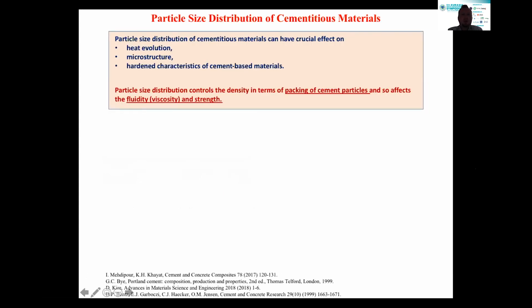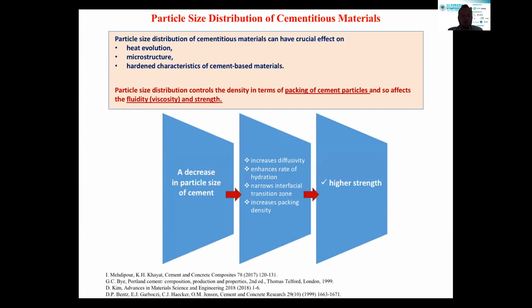structure. So what's the importance of the particle size distribution of cementitious materials? Particle size distributions have an effect on the heat evolution, microstructure, and hardened characteristics of cement-based materials. So the particle size distribution controls the packing of cement particles and also affects the viscosity and strength of the cement mortars. When the particle size of the cement decreases, we have higher diffusivity, higher rate of hydration, a narrower interfacial transition zone, and it also increases the packing density. So finally we have higher strength for the cement mortars.